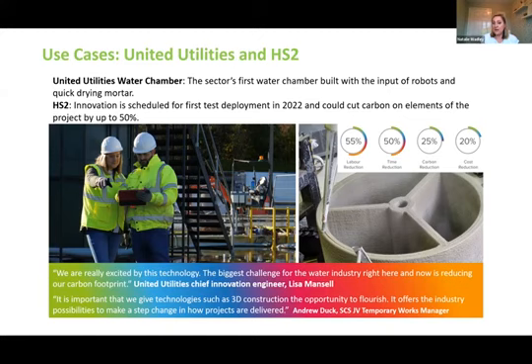And you can see some of those stats there that back up what I've been saying to you about. One where you can see the robot, the printer head there, extruding round in a tool path that allows you to print in one structure. And again, you're able to then look at some of those efficiencies. That chamber itself was fully printed in about 3.5 hours. It took about 7 days before we were prepared to safely crane it onto the demonstration site. But if you can appreciate that, if that was printed in situ on site, you've got something that's load bearing within an hour of being printed. So we're really excited about the technology as much as we are about the impact that we believe we can start to make.